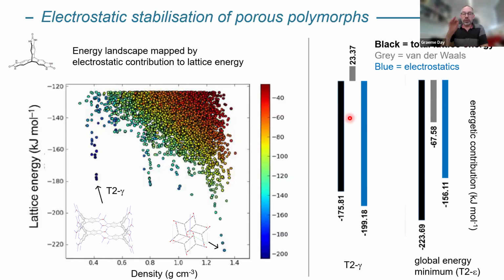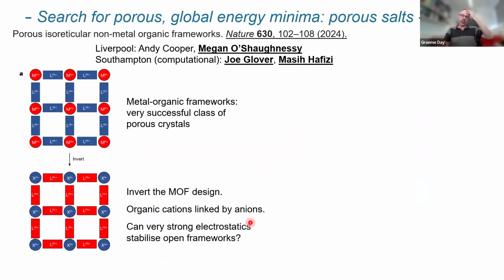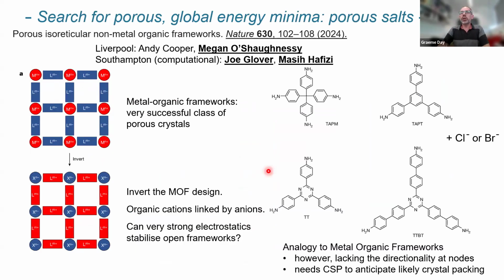And what we decided from this was, if we could make electrostatics even stronger, then we might be able to get to a point where the low density porous structures come below the high density close packed structures on a landscape. The approach we took for that was to look at things with net charges on our components. And we were a bit inspired here from metal organic frameworks, which are a very well-used class of materials where you have organic linkers with a net negative charge bonded to net positive charge metals, and you can end up getting these porous frameworks. We decided to try to do something sort of by analogy to that.